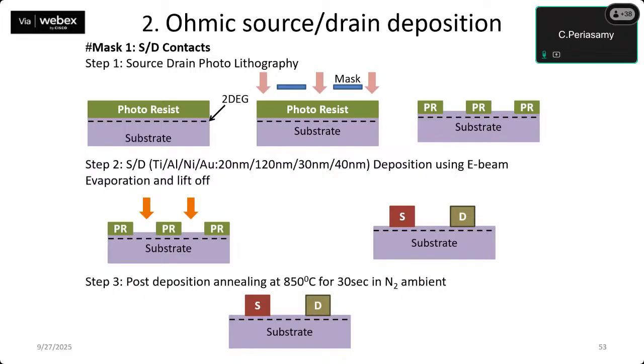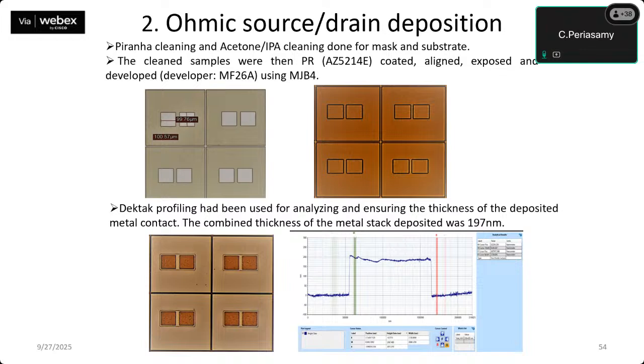the deposited source and drain metal contact to avoid surface defects. That post-annealing was done at 850 degrees for 30 seconds in an N2 ambient. One can choose either N2 or argon. So this is the ohmic contact after fabricating it on the stack surface. Then we have measured the corresponding thickness using the thickness measurement setup, and we have verified the stack layer. Not only that, for both ohmic and Schottky contacts we have measured the deposited metal contact thickness, not only for source and drain. After depositing the gate also, we ensured the deposited thickness of source, drain and gate.